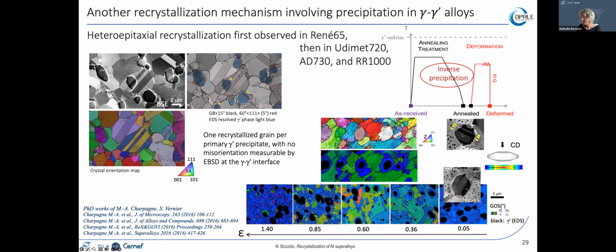And because of this, recrystallization of this type begins very early during deformation, because there is no need for forming a nucleus, because the nucleus is actually already there before starting to deform. So as soon as you start deforming at very low strain levels, you would immediately see that these recrystallized grains start developing.